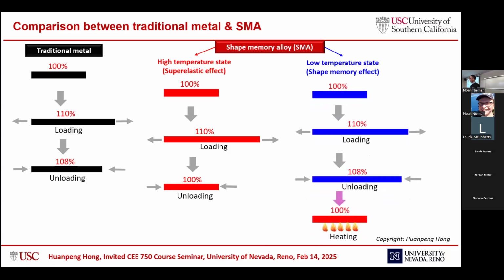And when it's in the low temperature state, it will exhibit the shape memory effect. The first three steps are the same: loading to 110%, unloading, it will end up at about 108%. And the magic thing is that if we heat this material up, it will completely go back to the original shape. It's like this material can memorize its initial length. So that's why we call it shape memory effect, shape memory alloy.